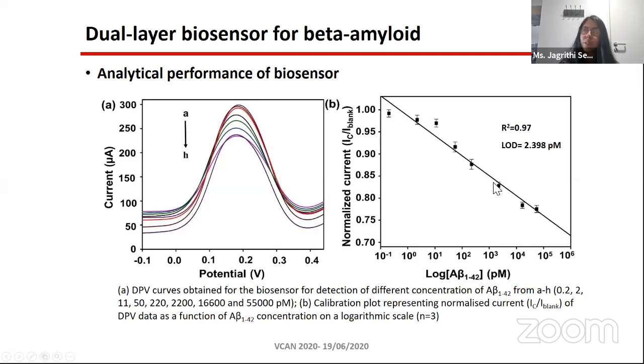Okay, and this is the analytical performance of our biosensor. These are the DPV responses for a range of concentrations that we tried, from 0.2 to 55,000 picomolar, 55 nanomolar. We saw a very nice calibration plot between the concentration from approximately 11 picomolar to 55 nanomolar, and the limit of detection that we estimated was around 2.398 picomolar, or 2.4 picomolar, which is really good because most of the beta amyloid biomarkers in blood are usually in the range of 10 to 20 picomolar in the early stages, and it keeps on decreasing as the stages progress. So in the later stages, it can go really low, in the picomolar range, or even in the femtomolar range.